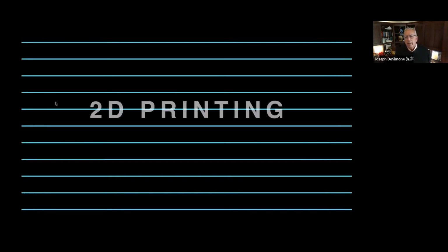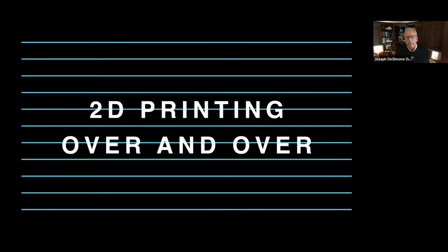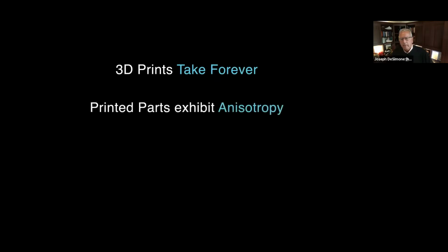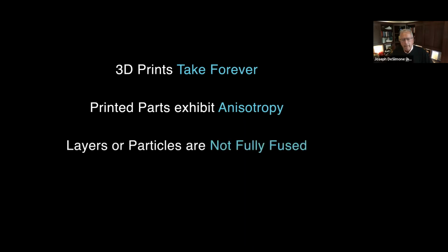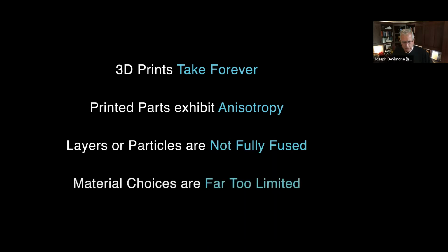And so I think all these processes are clearly layer by layer approaches. And I think 3D printing is often better thought of as 2D printing over and over and over again. And the challenges relate to the fact that it takes a long time. It's still pretty slow. Because of the layer by layer approach, there's anisotropy intrinsic to the properties. And because for polymers especially, the lack of full development of chain entanglements between layers and particles is a challenge, and the material choices are far too limited.